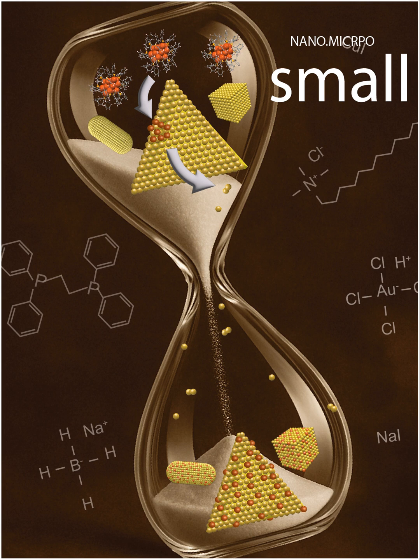The original cube and rod shapes were beautifully preserved. No distorted cubes or bent rods? Nope, perfect preservation. And again, EDS mapping showed the gold and copper were mixed homogeneously inside these shapes too. They got about 36% copper in the cubes and 22% in the rods in their examples. So the method doesn't seem to care what the starting shape is. Exactly. And that's a big deal.